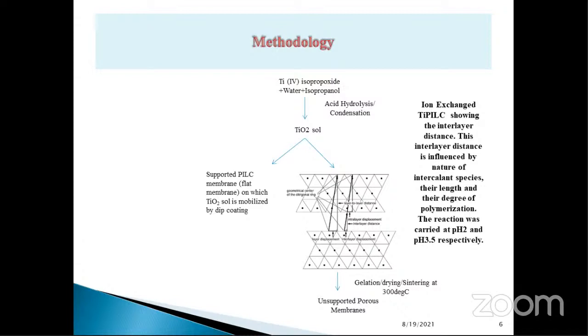We have chosen 2 different pH to ascertain the structure of the membrane material. So that underwent acid hydrolysis and condensation to give the titania sol. With the titania sol, we have made the supported membrane material and the unsupported membrane material.